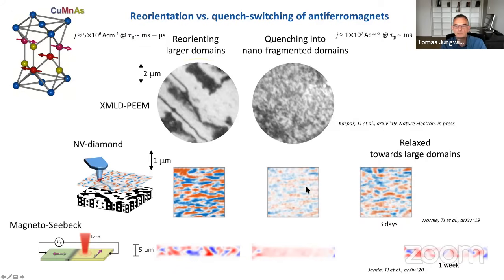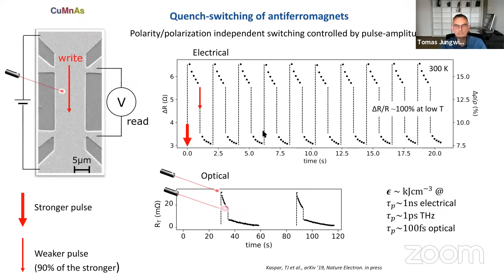the system. And what we see is that the system tends to reconstruct after some time these large domain states, which then is the equilibrium state. So the nano-fragmented domain state is metastable. However, we can deliver these short pulses, and these nano-fragmented states remain in this metastable configuration for macroscopic timescales. So this is the microscopy image.